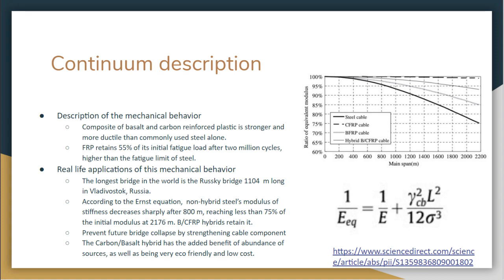Now, this isn't a problem for the average sized bridge, but once that length reaches over 800 meters, non-hybrid steel's equivalent modulus of elasticity starts dropping drastically, falling to only 75% of its initial modulus after 2176 meters, as you can see in the Ernst equation. BCFRP are impervious to this because of their low weight density gamma. Because steel is so much more dense, it does not stand the test at long distances, so we hope to strengthen future bridges by strengthening the cable component with specifically BCFRP.